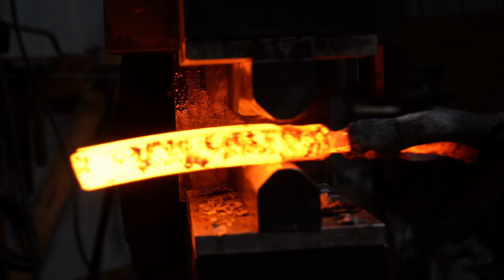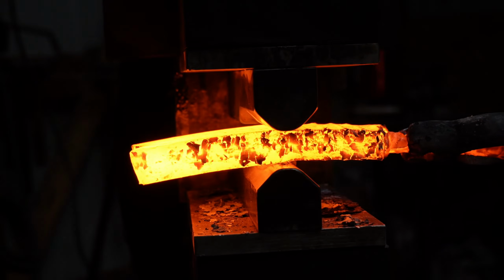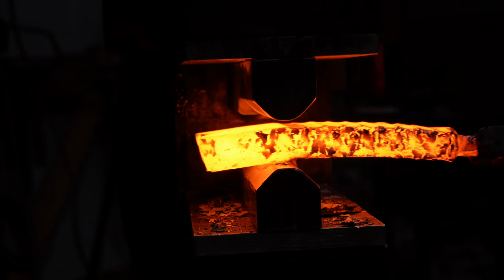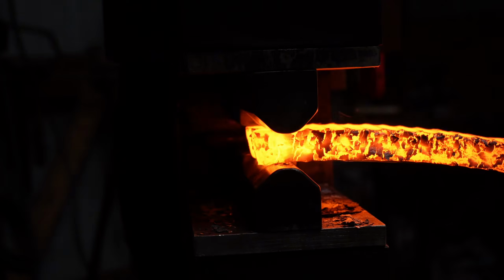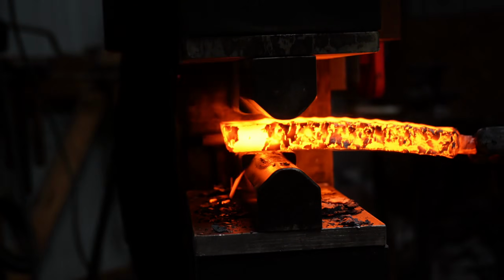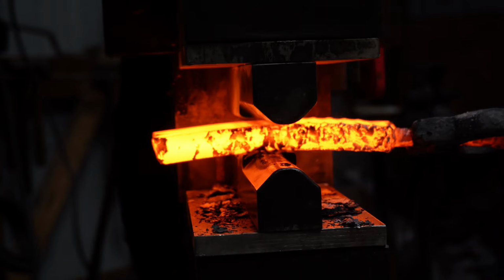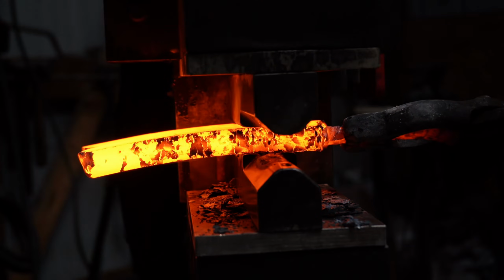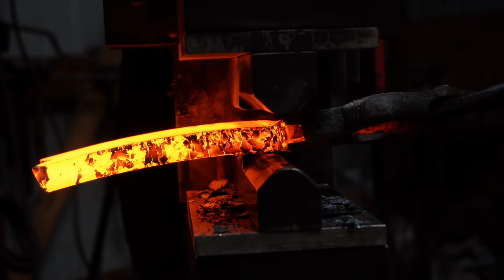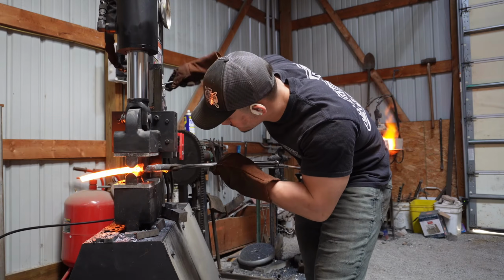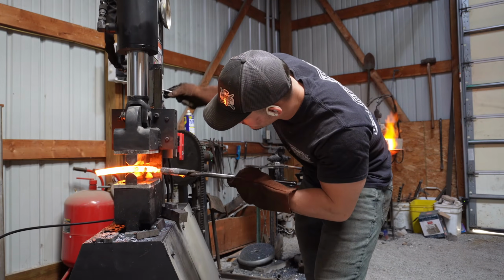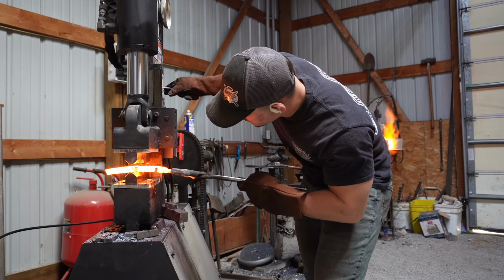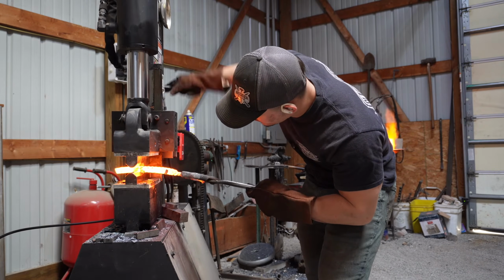Now, this is actually one of the most risky parts of this entire build, just drawing this billet out, because you have to remember there are weld seams running parallel to the drawing dies the entire time that I am drawing this billet out. This means that if I apply too much pressure, if I try to forge it when it's too cold, or if I don't get it hot enough before forging, I could split open one of those seams, which would ruin the entire billet.